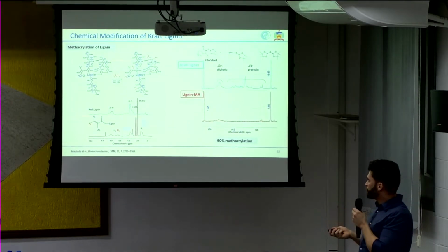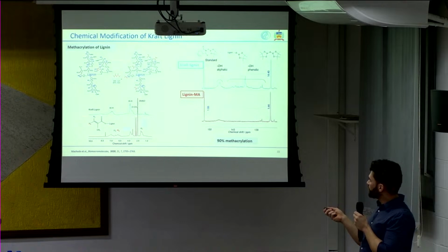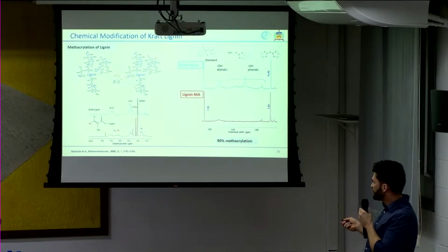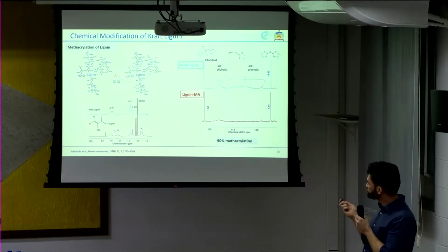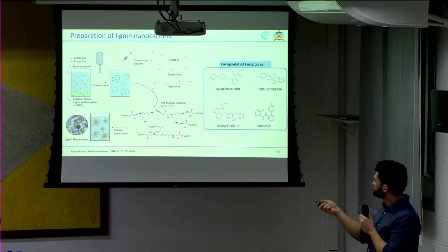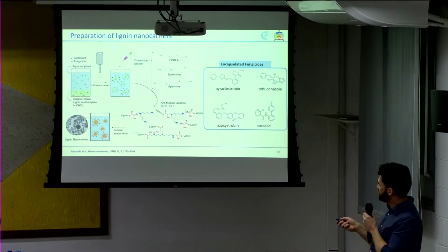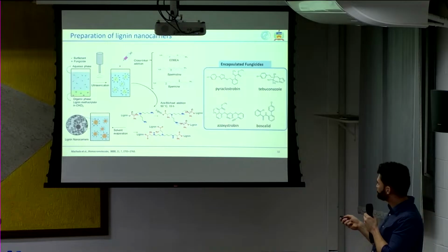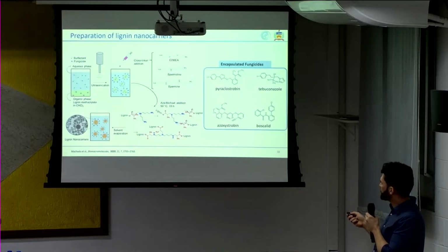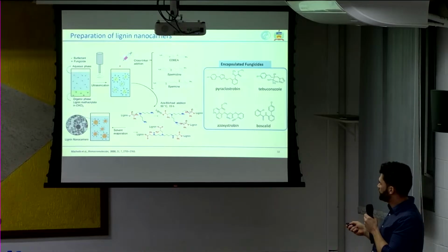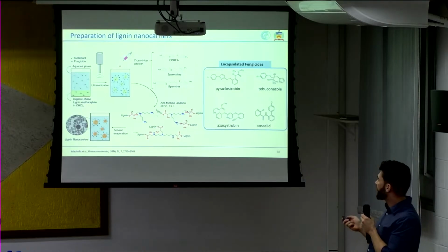So how do we make those particles? So we chemically modified lignin with methacrylation. So we have Kraft lignin here that's actually a waste from the paper industry. And then we do a methacrylation reaction. And after the methacrylation reaction, we got 90% of methacrylation calculated by NMR. And to make those particles, we use miniemulsion polymerization. And so we have the lignin methacrylate in the organic phase, and also the encapsulated fungicides in the organic phase. And then we use amine crosslinkers with different functionalities to do a Michael addition cross-linking and form the nanocarriers.